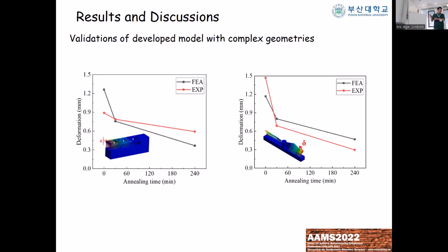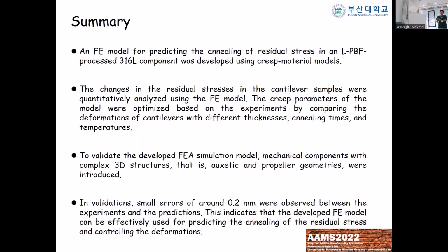And overall, there is good agreement, but it's just at one point, not for the heat treatment but for the as-built state, which is, I think, because this structure was probably too thick. So before we cut the supporting structure, maybe this was a little bit bent, I think. It's at this point; overall, there was good agreement.